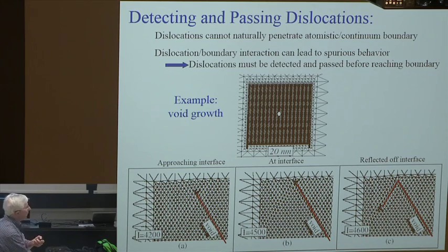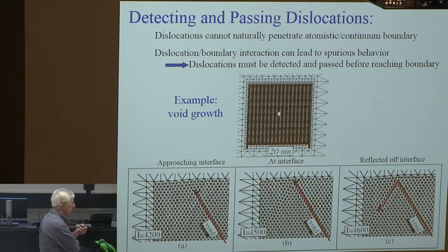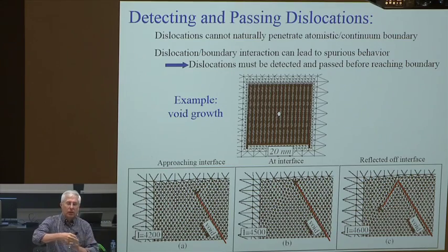Now, for the plasticity parts of the problem, we have to worry about the dislocations. If I have an atomistic dislocation, it corresponds to shearing of atoms. It corresponds to 100% shear strains. But finite elements is a small-strain elasticity problem. It's linear elastic, so I can't possibly shear something by 100%. The stress for that would be the elastic modulus. So the finite elements themselves can't handle an atomistic shear.